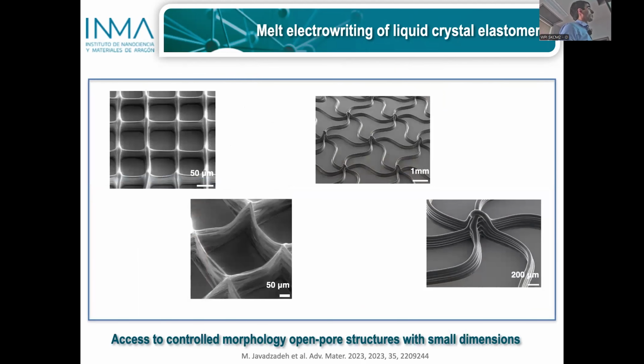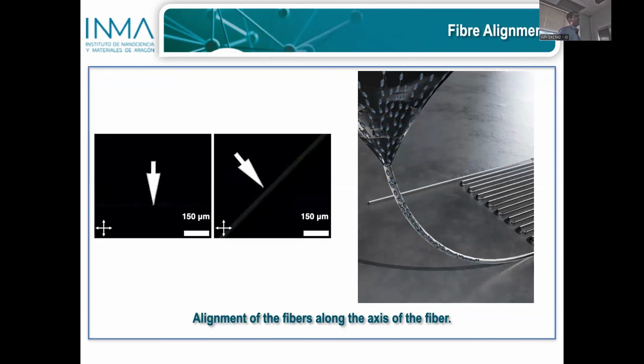As a result, we were able to get structures that you can see here, in the order of 100 microns. Actually, we now have much smaller ones, with fibers in the order of a few microns and spacings in the order of 90 microns. You can also build up walls of material and also go to curved structures. Again, as in the case of conventional 3D, 4D printing, this drawing of the fiber towards the collector generates birefringence, generates alignment in the fiber.